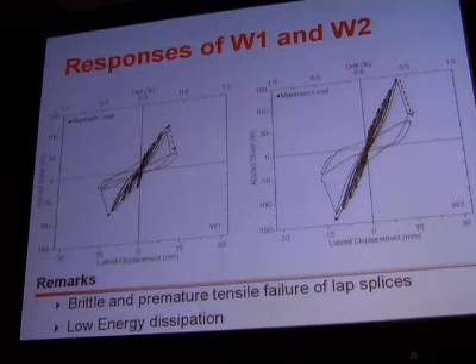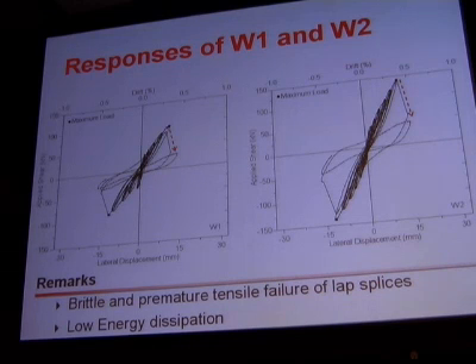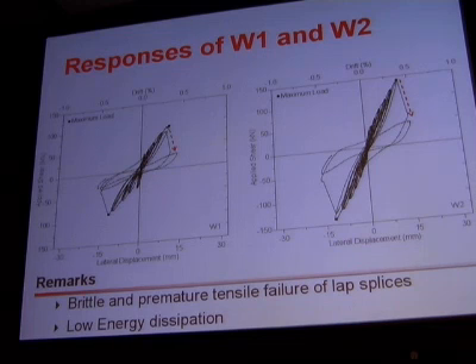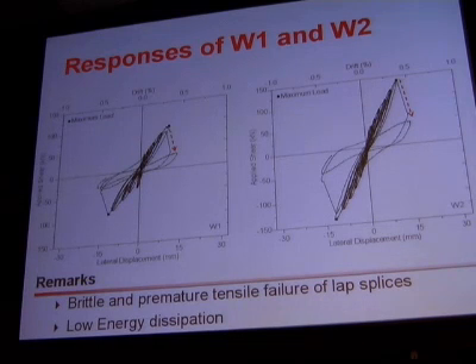The responses of W1 and W2, they didn't reach yield. And, you know, if it were monotonic loading, they may have reached yield and had some ductility. But because of the reverse cyclic loading, we get a brittle type of shear failure. We get inadequate amount of energy dissipation, both for W1 and W2. W2 had a larger amount of flexural steel and therefore has a higher capacity. But both of these are inadequate in terms of performance.